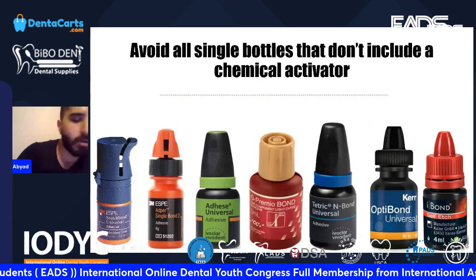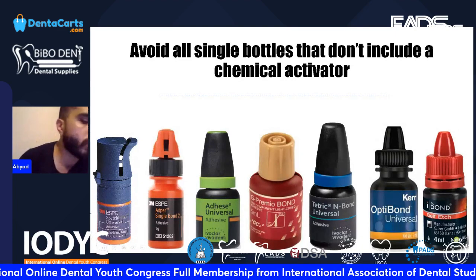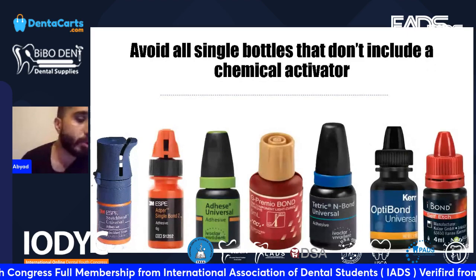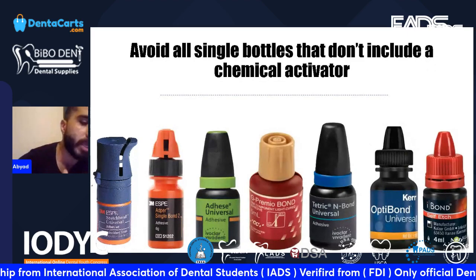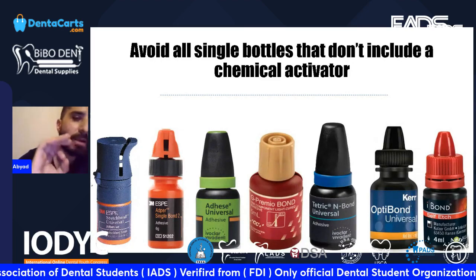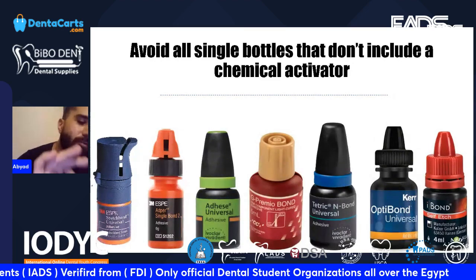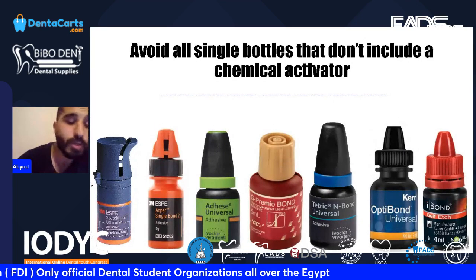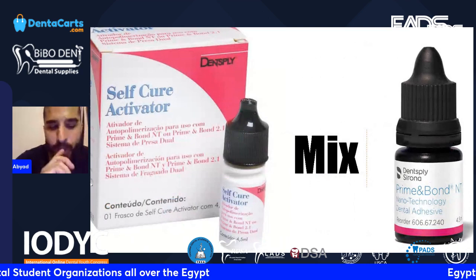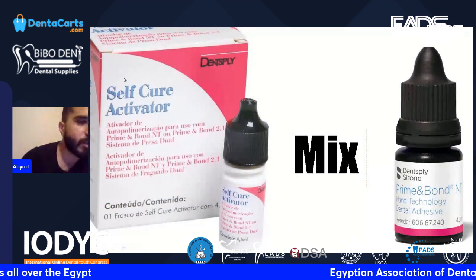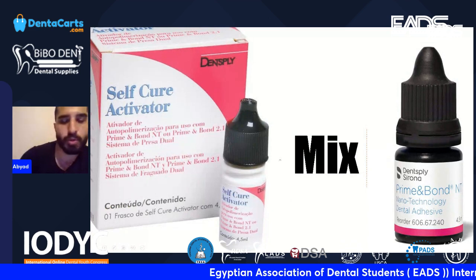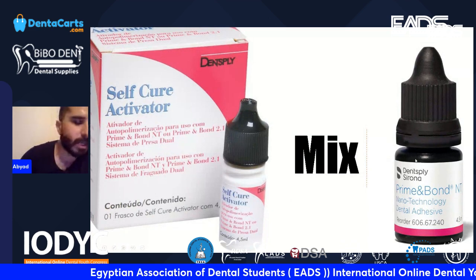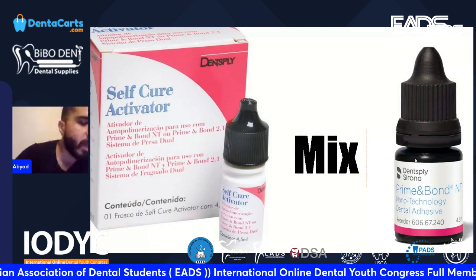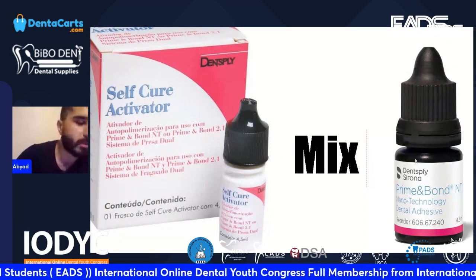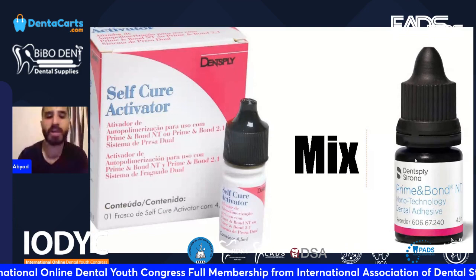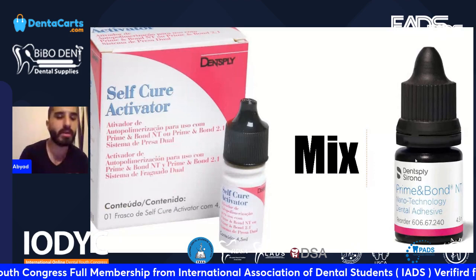We all use them. All of them don't work well when you are trying to utilize a dual cure resin cement. You have to couple it with a chemical curing agent. Okay, all single bottle light cure adhesives need to be avoided when you are trying to utilize a dual cure resin cement. So we know that some companies release a self cure activator, so you can simply use their adhesive and add few drops of the self cure activator, and you're safe. You can use it with a dual cure resin cement. Always remember, dual cure resin cement, the adhesive should be dual cure, should not be single bottle light cure.